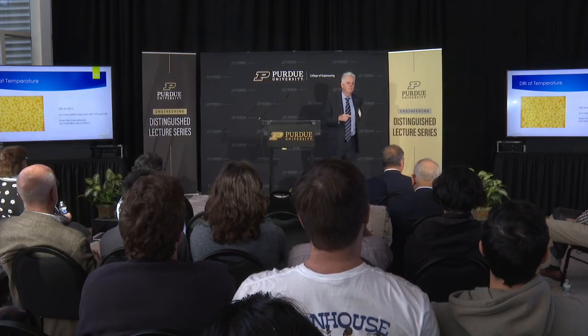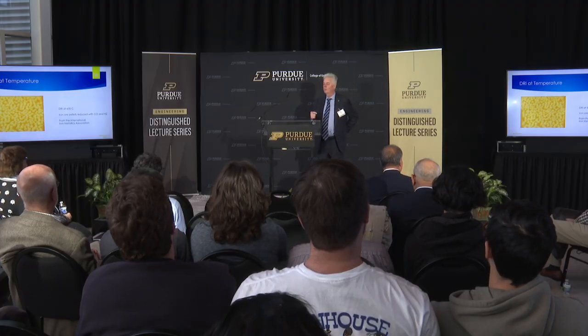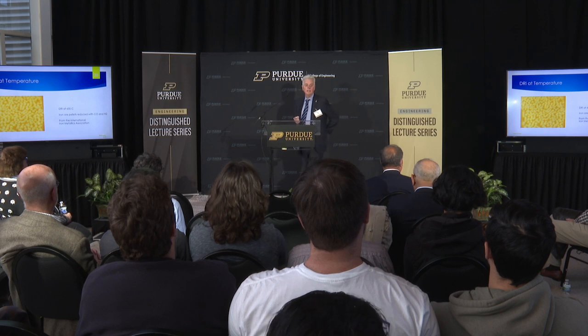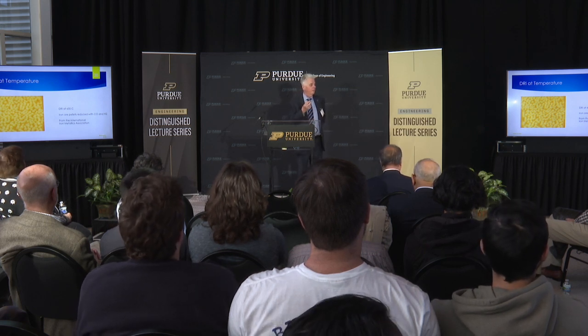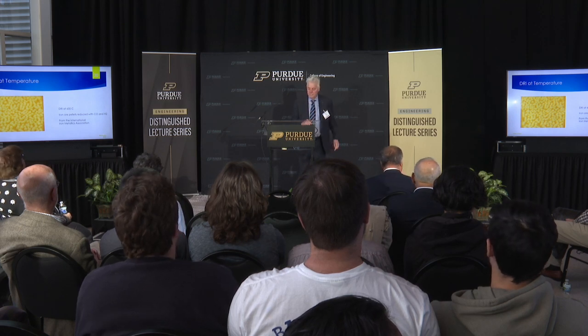And the amount of iron you have depends on how long it's sitting. So it's, you know, 98% iron when you get it. 2 weeks later, it might be 97%. A month later, it might be 93%, etc. So transportation of this is important if you're a steelmaker because you're losing it by it reverting to its natural form because it has a lot of surface area. And then if it starts to heat up, it reacts faster. So this is a problem with DRI.